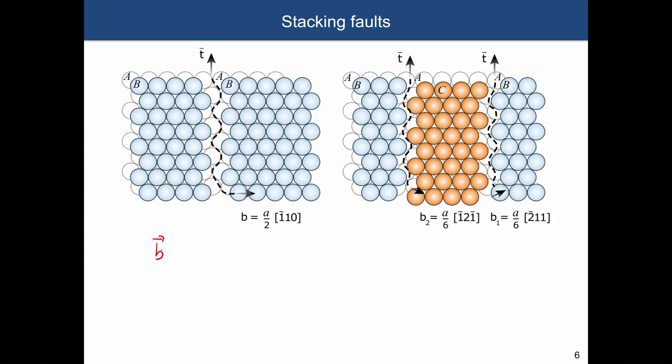And we mentioned perfect dislocations in materials, for example in FCC crystals, with a Burger's vector of a perfect dislocation. This dislocation can dissociate into two dislocations if their elastic energy is lower than the elastic energy of the initial dislocation itself, right?